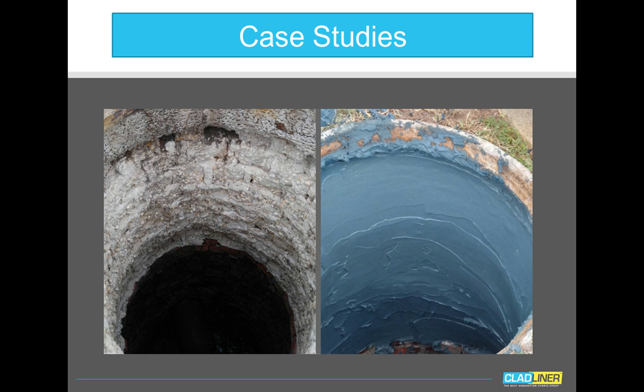The manhole was power washed to remove all this. In some cases, we felt like it was not structurally sound, and being a brick manhole was very rough. So the contractor at that point determined that it made more sense to first resurface it with a high compression, 10,000 psi sewer grade resurfacing mortar.